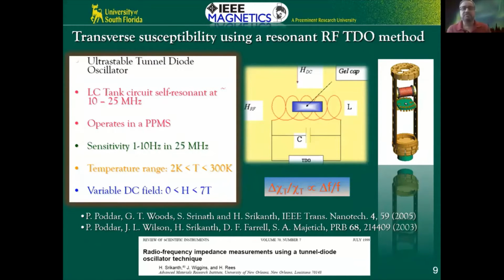Here, I would like to introduce a technique that we developed in my lab many years back, but it turns out to be one of the best and most sensitive ways of measuring the magnetic anisotropy in nanoparticles, as well as in films or any kind of materials, any kind of magnets. What we do here is use transverse susceptibility, which is based on what is known as the tunnel diode oscillator, TDO. Essentially, we build oscillators. The sample sits inside an inductive coil, and it's an LC circuit. It's nothing but a tank circuit.